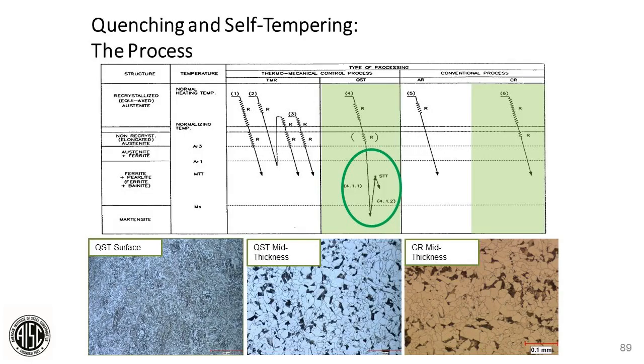And this is another quick look at what's happening. At the QST surface, we have a tempered martensite. At mid-thickness, we have a little bit more fine grain going on, but the control rolled mid-thickness would be a little bit coarser grain. But this is a good look at what's happening in this process. Next slide.